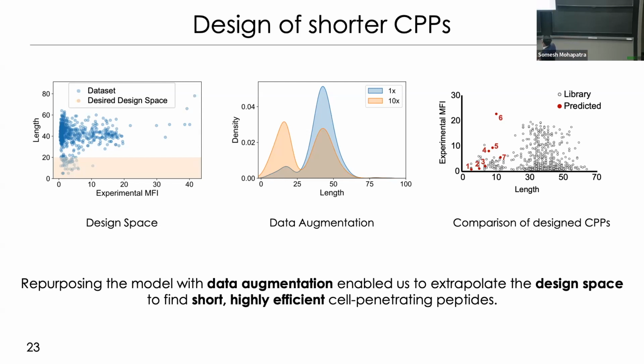Instead of this blue curve, which the data set was, we showed a bimodal distribution to the machine learning model. We showed it multiple times the peptides that were shorter in length, such that the model was biased to knowing what shorter peptides look like. And at the same time, we showed it an equal amount of times the longer peptides, which were more active in general. So the model was biased towards designing shorter but efficient peptides using this data augmentation approach. And in this way, we were able to discover a critical peptide of about 11 amino acids with a 22-fold or 25-fold activity actually.